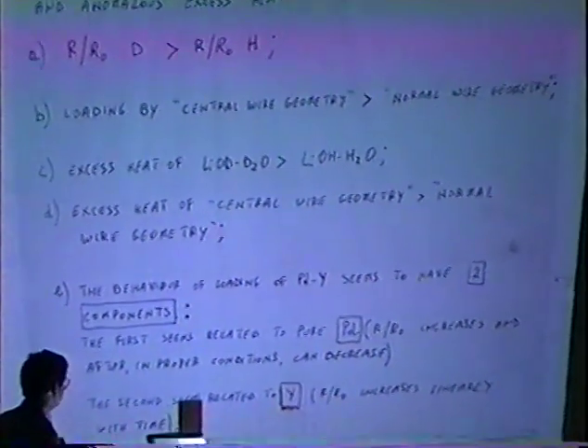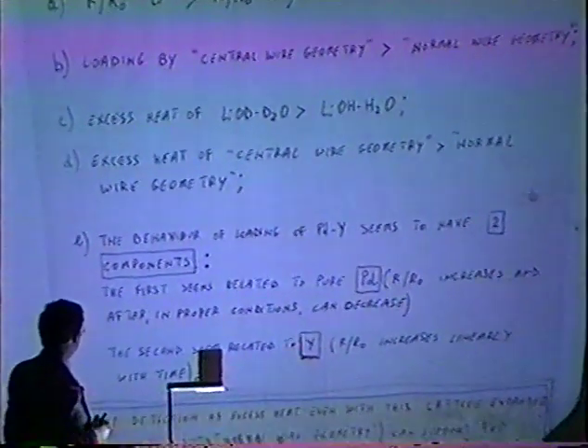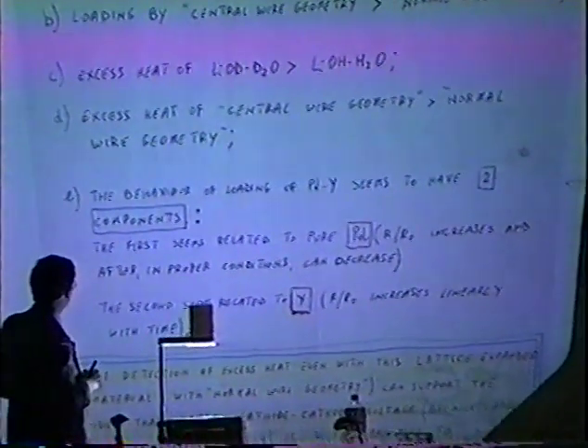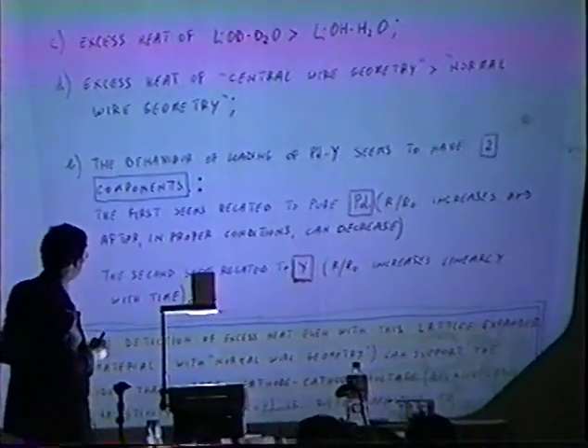The main results are the following. We observe that the resistance ratio with deuterium is larger than with hydrogen in this material. The loading of the central wire geometry is larger than the normal wire geometry. Excess heat of heavy water is larger than light water. And the excess heat of heavy water in central wire geometry is larger than in normal wire geometry. So these are correlated.